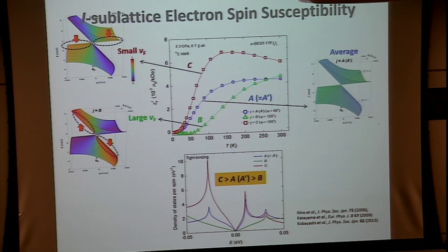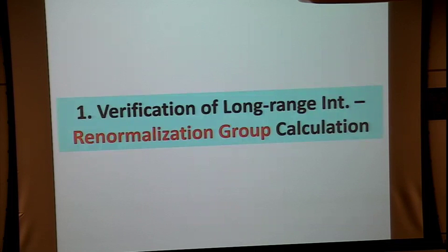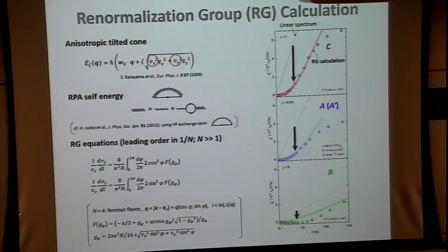as predicted by Abrikosov. So students performed renormalization group calculations. This is the tilted Weyl equation. In the isotropic case only these terms are there, but this omega 0 and q describes the tilting. And this Vx and Vy is renormalized by long-range Coulomb interactions. And he calculated the one loop and the large N expansion. And this is the RG equations.